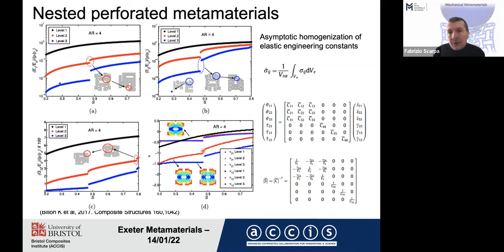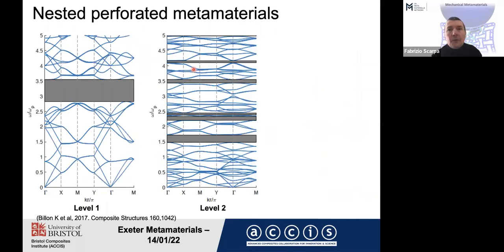auxetic. You see the discontinuities over there on the different engineering constants that are calculated using asymptotic homogenization by finite elements, for this value of S of 0.5. This is because for this interspace ratio, we have a transition of the mechanism that goes from pure stretching to pure hinging at the interface. You can also see that we always obtain different in-plane compliance. The structure becomes extremely soft. But this is also one of the reasons why it can be quite interesting for band gap and wave propagation control, especially at lower frequencies.